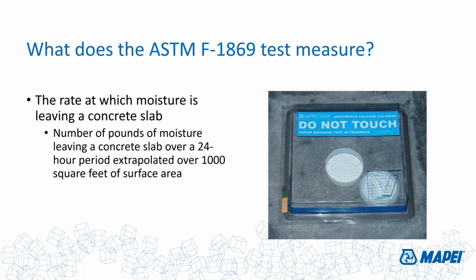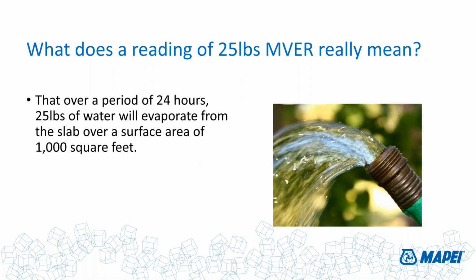That number is reported in pounds of moisture leaving a concrete slab over a 24-hour period, extrapolated over 1,000 square feet of surface area. Okay, so this is the test that has been around forever, probably followed the rubber mat test or some other things, but this is a way to quantify the rate at which water is leaving the system. Okay, so what does that really mean? That tells you how much water is evaporating out of the slab over a period of 1,000 square feet. So we all come up with numbers.